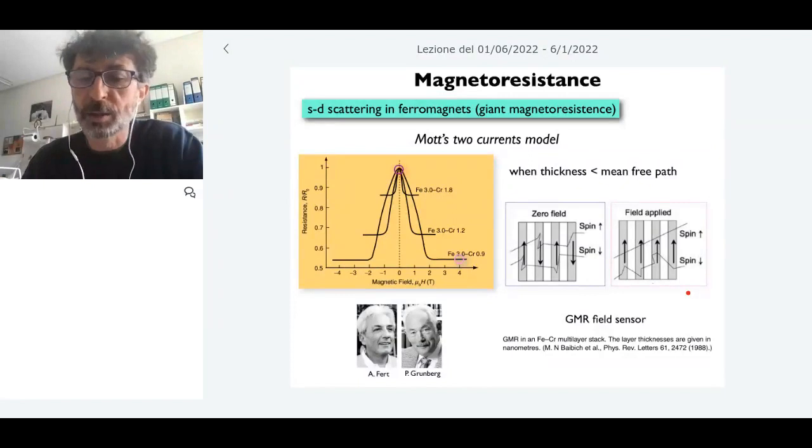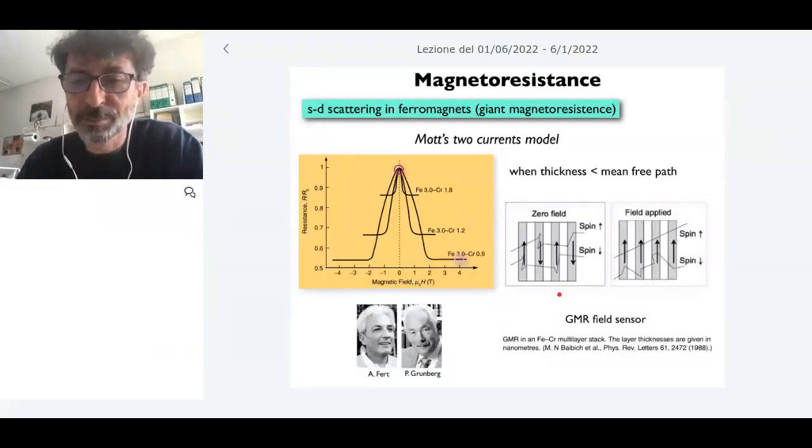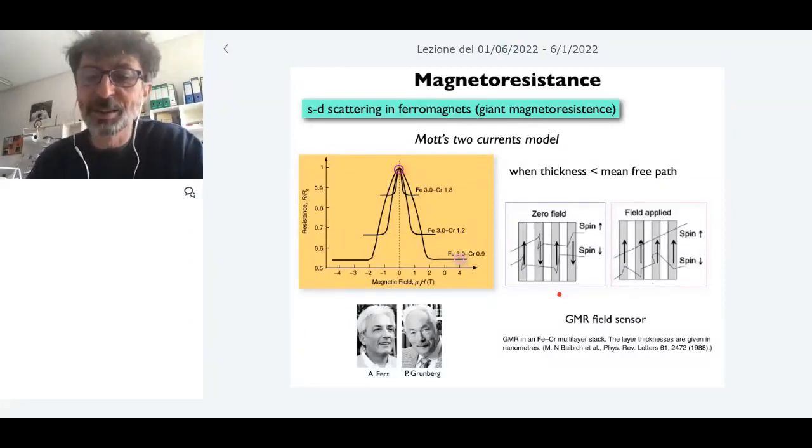This is the original result of the paper of 1988. They used a multilayer of iron and chromium, and they used a trick in order to have, at zero field, a situation where the magnetization is antiparallel. And then with the applied field, they could orient it, and they essentially used an interaction called RKKY, to have an antiferromagnetic interaction between the different layers.